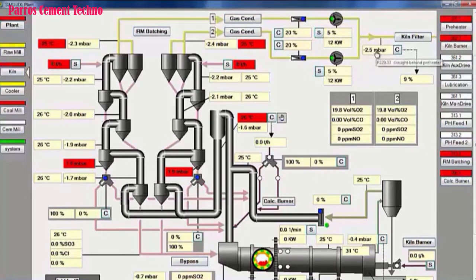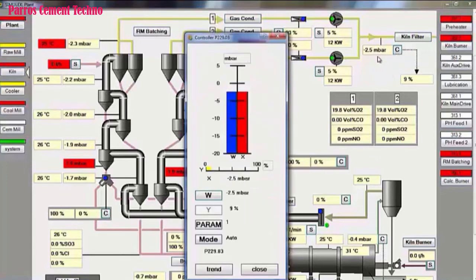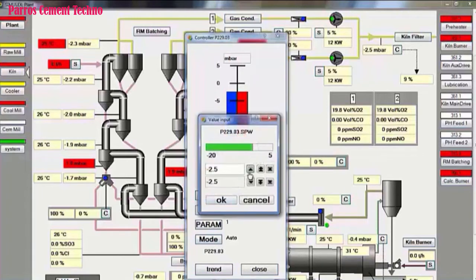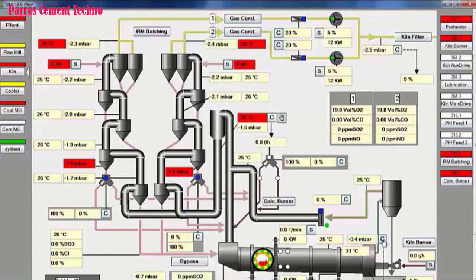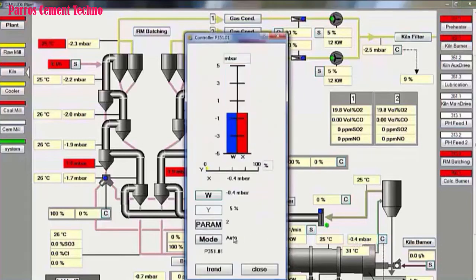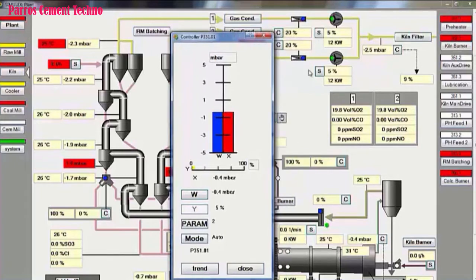Before starting the firing of the main burner, it is recommended that the draft behind the preheater be given an automatic position with a setting of -1.5 to -2.5 millibar, so that when we add damper openings or increase the rotational speed of the SPID fan, the rotational speed of the kiln filter ID fan will increase automatically. Then the kiln head draft is also given an automatic position with a setting of -0.2 to -0.4 millibar, so that when we add cooling air from the cooler, the cooler ID fan damper will increase automatically, and adjust to the kiln head draft setting.